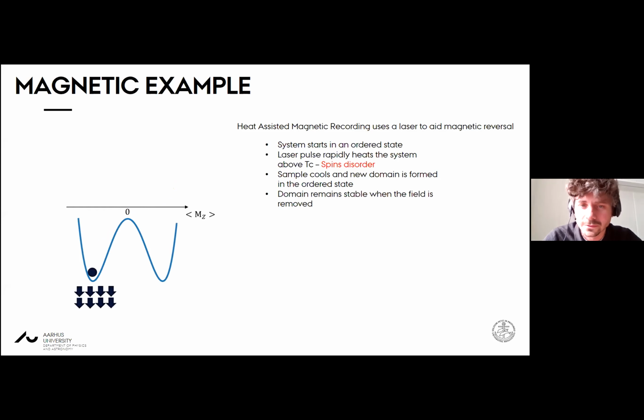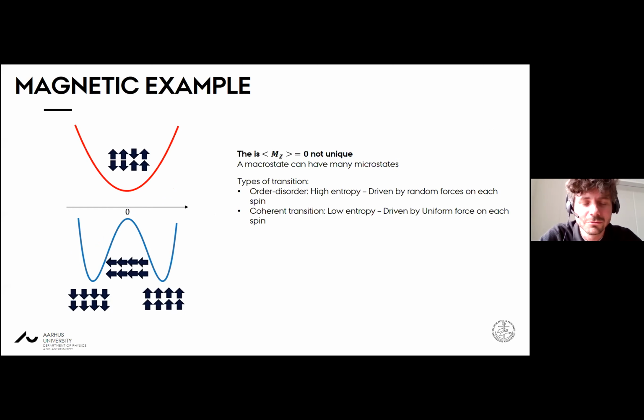Okay, so what is interesting is we have two routes suggested here, and obviously there's a continuum between both extremes, in which the system passes through a state where MZ is equal to zero, but there's not a unique MZ equal to zero state. So that macro state can have many microstates. And the two cases I've shown here are a system which goes via a high entropy state to generate the inverted state, or there's a coherent low entropy state in which there's a uniform rotation of the spin system.